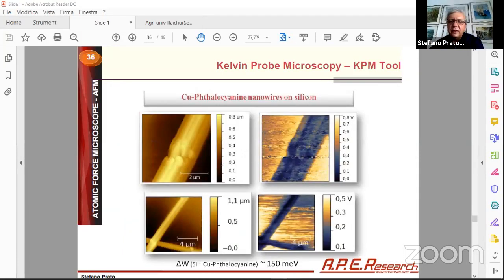This is relevant, for example, for biological application, when you want to study molecules or other things. This is very important because, for example, this is some molecules that aggregate into wires. When you drop cast this molecule on top of a surface, in this case silicon, those are some copper phthalocyanines, and those aggregate to form some nanowires, okay? And with the Kelvin mapping, you can see that this material is really different from the substrate, okay? And with the Kelvin probe, you can study if there are some defects, for example, you can study how uniform the work function is along your material, okay?